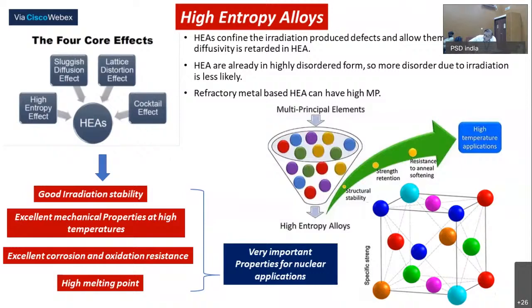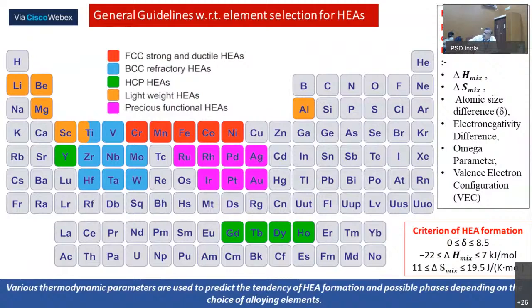So we thought about all these points and we started looking for the possible elements. If you look at the right bottom, you can see the configuration of the high entropy alloys. What should be the structure? The difference between the atom sizes should fall between 0 to 8.5. Enthalpy of mixing should not be very high, otherwise you will end up with intermetallics. Entropy should be as maximum as possible. That's the way, if you start looking theoretically, you can map on the entire periodic table which elements are possible to get high entropy alloys.